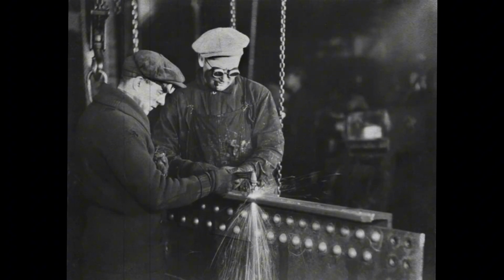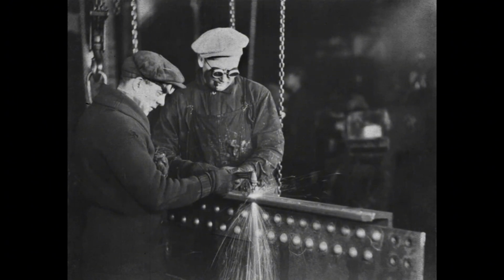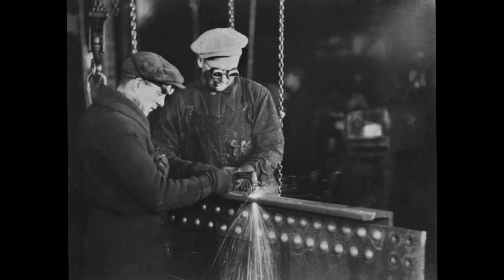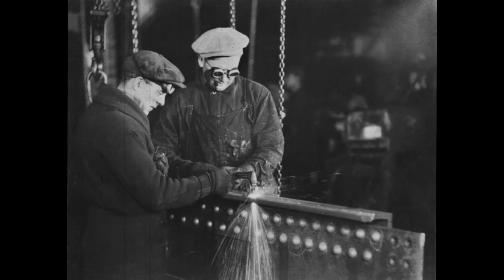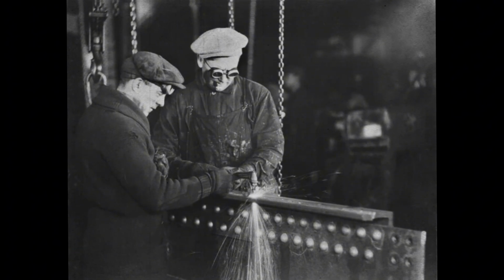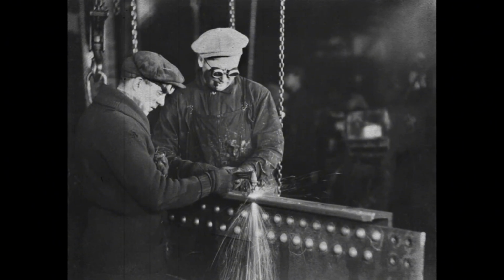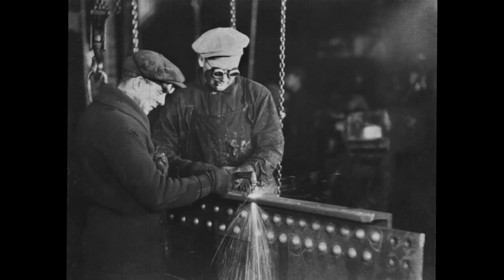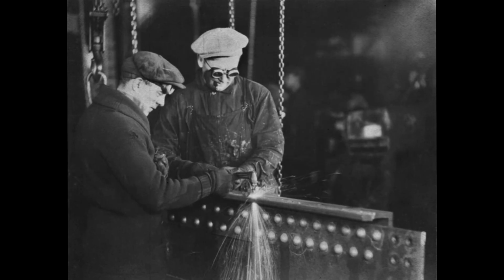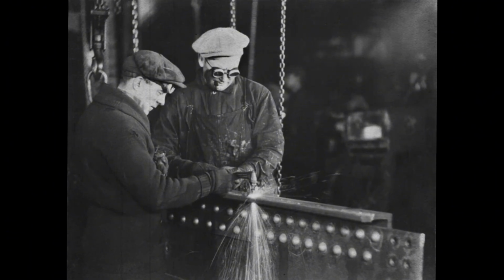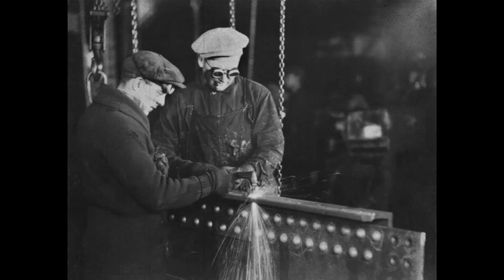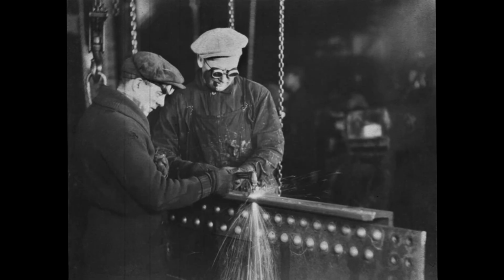Traditional stud welding relied on capacitor discharge to create instantaneous high current flow that generated intense heat rapidly, but with limited control over the thermal cycle. Nelson's drawn arc method used a controlled arc that could be sustained for precise durations, allowing better control over heat input rates and cooling rates that affected the metallurgical properties of the weld zone.